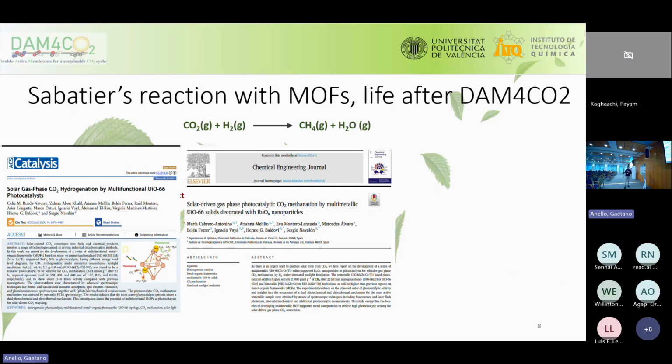And what we are making with the changes that we are inducing to the MOF is that while we are keeping the crystal structure, we are playing with the bandgap of the MOF, but also the valence band position. Okay, so playing with the valence band position and the bandgap, we are able to increase the productivity of the composite.